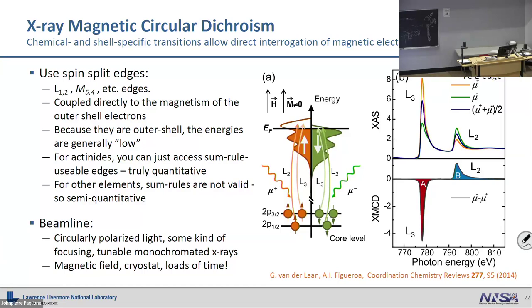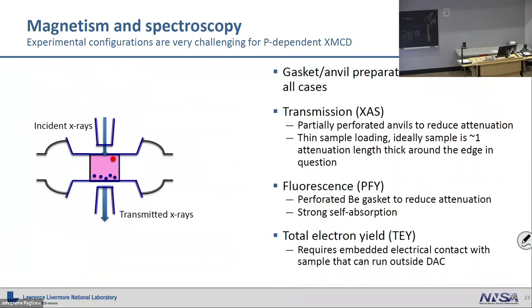When you go to things like rare earths, this gets a little easier because the magnetic electron is the 4Fs, and those are down in the core. And so that excitation becomes an L excitation. And so that, in this case, like an L2, but it's down with the rare earths, and that starts then coupling better to the magnetism. Technically, the 4F one is like an M edge or something like that. If you go to actinides, actually you can get to the M edge, which is the magnetic excitation.